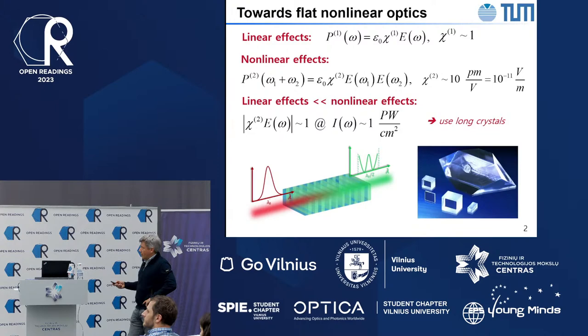Normally, nonlinear effects are weak effects. When I say nonlinear effects are weak, we can compare them with the linear ones by looking at the polarization term that is producing the linear effects, and that's the first order in the expansion of the polarization of the medium, P, with respect to the applied electric field, E. So we know that for linear effects, polarization equals epsilon naught, chi 1, the susceptibility of the material, times the electric field.